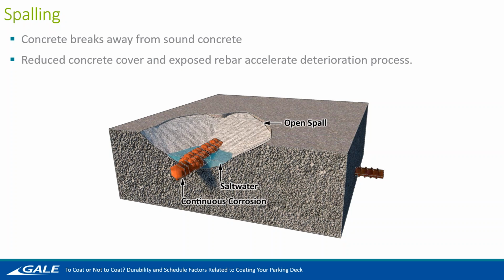So as the delamination accelerates, it eventually turns into a spall. As that corrosion keeps exfoliating, it's going to push that sound concrete off, and eventually it's just going to completely pop up and completely detach from the surface. Typically maintenance men will walk around and remove these loose pieces of concrete because they can be tripping hazards. If they're above, they can be fall hazards. So this is going to leave the rebar completely exposed.